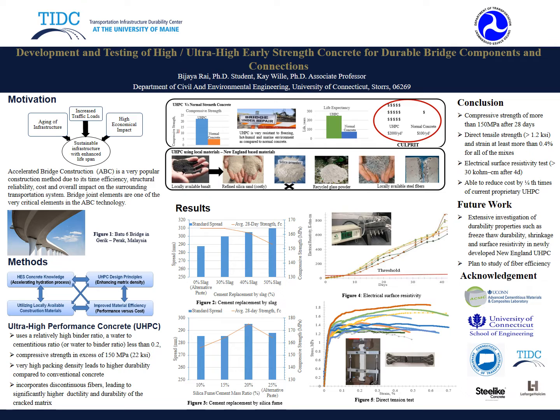Now, in conclusion, all the mixes have exceeded the compressive strength of 150 megapascal after 28 days. Direct tensile strength is more than 1.2 ksi, and strain is at least more than 0.4% for all the mixes. The electrical resistivity for all the mixes has exceeded 30 kilo ohm centimeter after 4 days, and we are able to reduce the cost to about a quarter of the cost of current proprietary UHPC, which is the biggest achievement from this research.